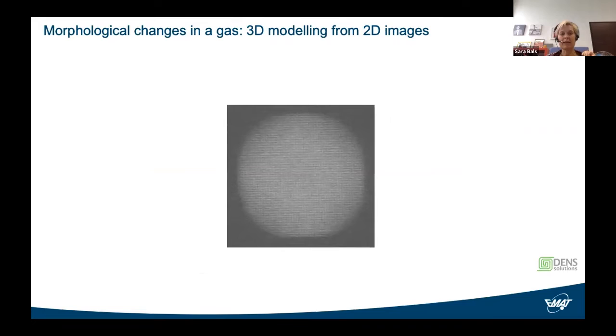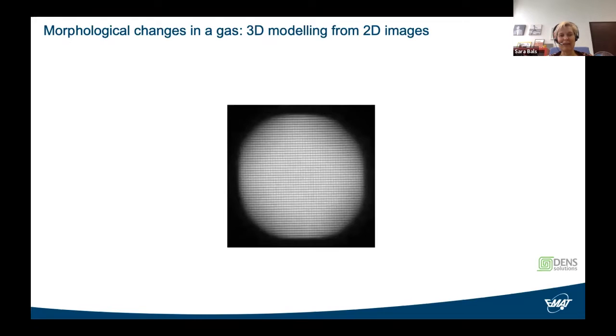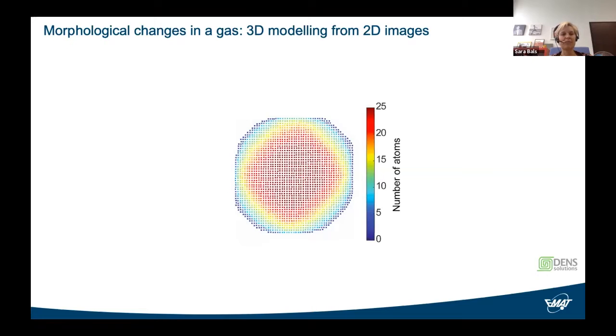Also, in the very last example that I want to share with you today, the three-dimensional modeling from 2D images was used. These are now platinum nanoparticles. They're in a gas cell holder. This holder does not enable us to tilt sufficiently for conventional electron tomography. And you also see that the contrast in this image is not as good as other images that I've shown. And the reason is simply that we are working in a gas. Think about driving in the fog. So first we're going to collect a series of images and we're going to correct for distortions, ending up with an image from which we can again count a number of atoms.